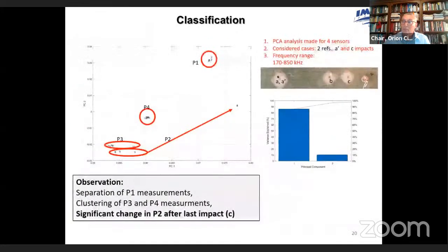As for the result of the classification, we can see that the sensors that are far away from the damage are clustered separately. So this is P1 and P4. The P3 cluster is over here, P2 is over here, and we have one more data point over here that is related to the last impact case. So here the damage to the plate was most severe. We had 4 impacts, and this case shows the largest differences.